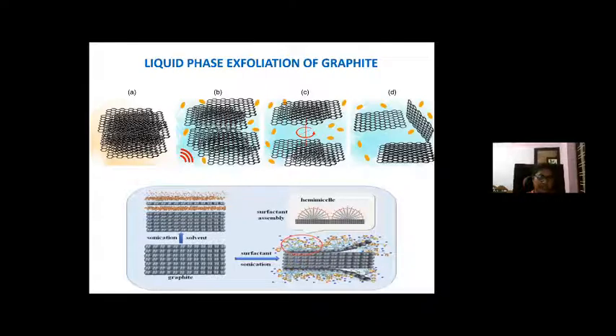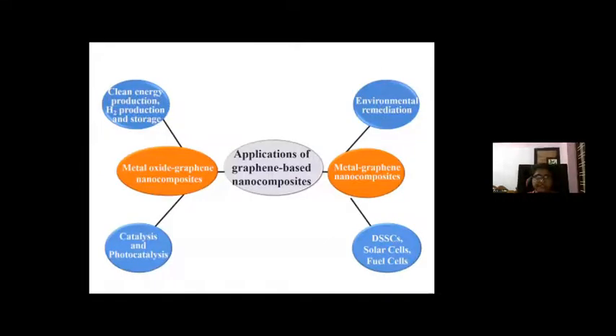To improve the yield of graphene, we can incorporate surfactants during preparation. In addition, surfactants can enable the use of water as a solvent for graphite exfoliation. In the present technique, we are using the surfactant Pluronic P123, which is a polyethylene glycol, polypropylene glycol, polyethylene glycol copolymer. And this is used in the presence of water for the exfoliation of graphite. The result is a high yield and the production of less defective, perfectly sp2 carbon-containing graphene sheets. And this graphene can be functionalized to form nanocomposites that can be used for a variety of applications, including catalysis.